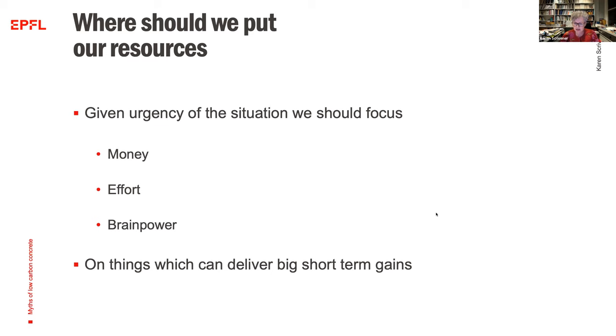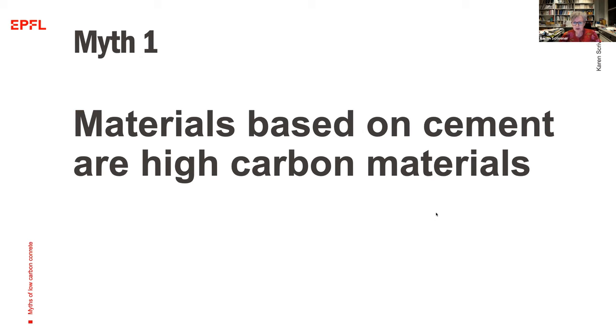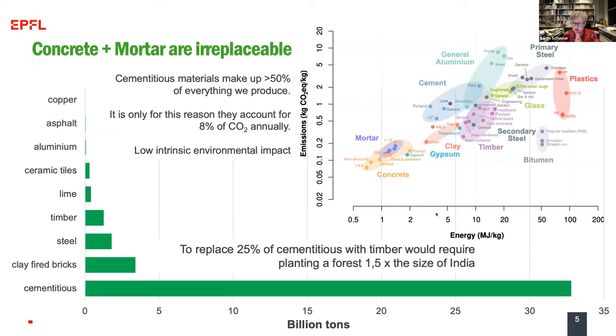So the first myth I'm going to start with is that materials based on cement are in fact high carbon materials. This is the impression many people have because globally, cement-based materials account for about 8% of world CO2 emissions. But this is purely because of the enormous amounts used. We produce about 30 billion tons of materials based on cement, that's to say concrete and mortars.